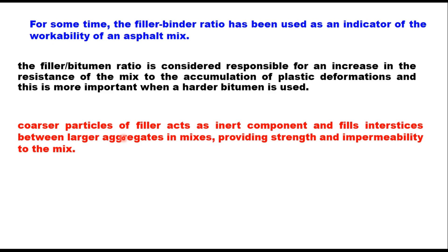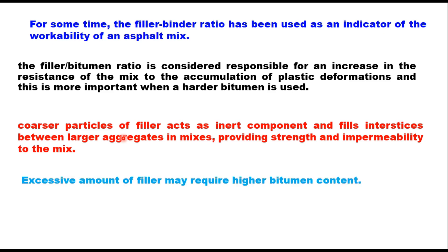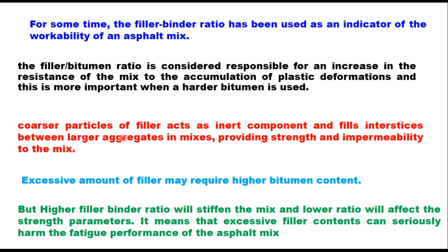Excessive amounts of filler may require higher bitumen content. A higher filler-binder ratio will stiffen the mix, and a lower ratio will affect the strength parameters. Excessive filler contents can seriously harm the fatigue performance of the asphalt mix, and if filler is excessive it is also responsible for plastic deformation — meaning both problems can occur: rutting as well as fatigue.